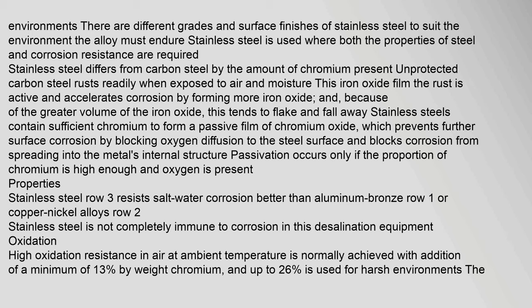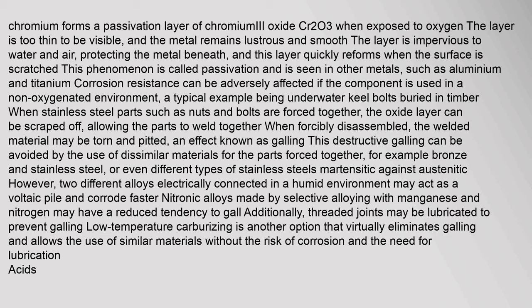Stainless steel resists salt water corrosion better than aluminum, bronze, or copper-nickel alloys, though it is not completely immune to corrosion. High oxidation resistance in air at ambient temperature is normally achieved with a minimum of 13 percent chromium by weight, and up to 26 percent is used for harsh environments. The chromium forms a passivation layer of chromium oxide (Cr2O3) when exposed to oxygen. The layer is too thin to be visible, and the metal remains lustrous and smooth. The layer is impervious to water and air, protecting the metal beneath, and quickly reforms when the surface is scratched. This phenomenon is called passivation, also seen in metals such as aluminium and titanium.